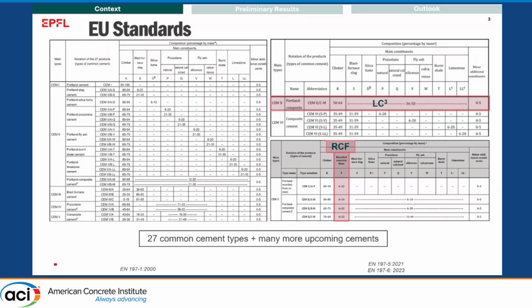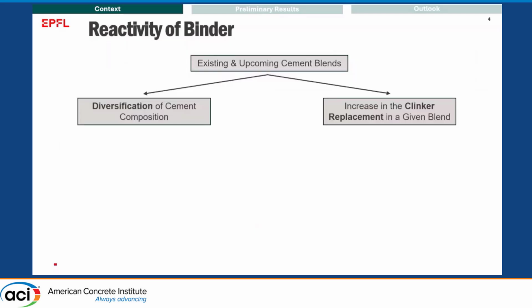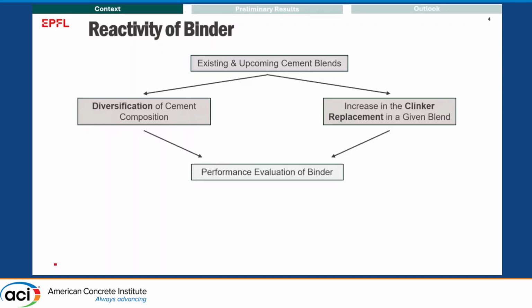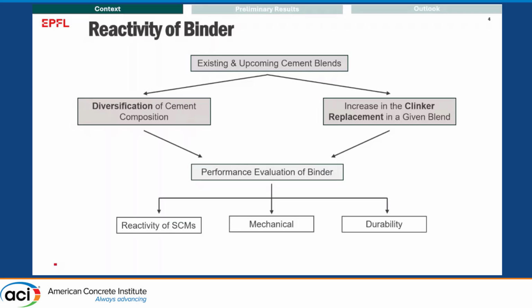But the main message is that there are a lot of common cement types, and there are many more upcoming cements. So what it implies for us is that the cement composition is being diversified, and there is also an increase in the clinker replacement for a given blend. So this calls for a good performance evaluation of binder, and this can be categorized in 3 main areas: reactivity of the SCMs, the mechanical performance, and durability performance.